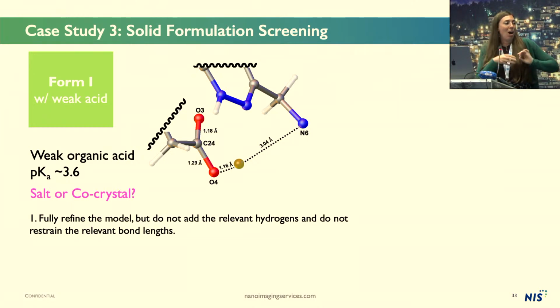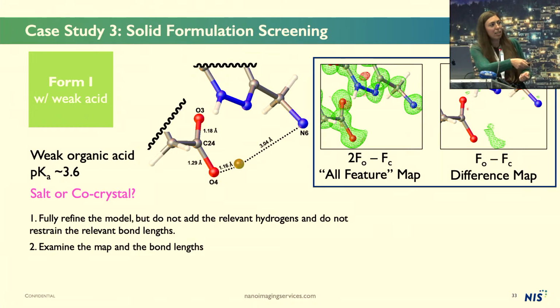And so this is what we did in this case, and we can see quite clearly that there is a little Q peak here in the structure that we solved, indicating that there might be a proton here near oxygen 4. And we also looked at the density maps. So the 2FO minus FC map showed a little point pointing in that direction near the oxygen. The nitrogen here was pretty spherical, I guess. And then the difference map showed quite a nice peak for this proton.